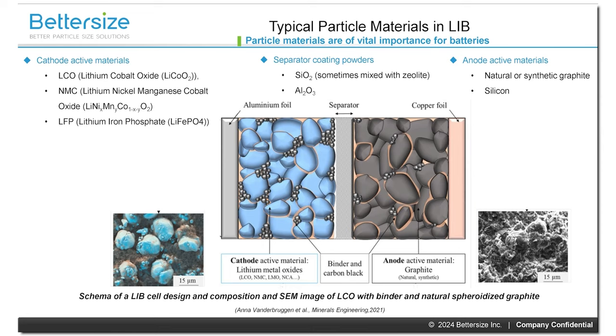The lithium-ion battery cathodes are comprised of active materials plus additives such as binders and carbon black to enhance the contact between the particles. These each offer distinct advantages in terms of energy density, cost, and safety. The most commonly used materials for cathodes include a variety of lithium metal oxides. These metals provide a stable framework for lithium ions to move in and out of during charge and discharge cycles.